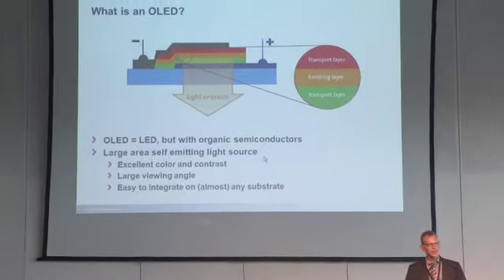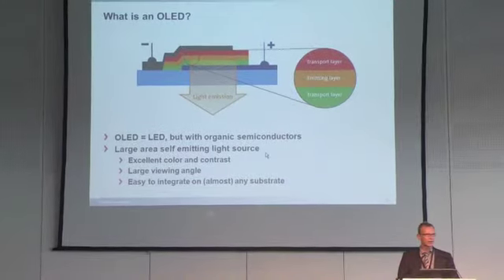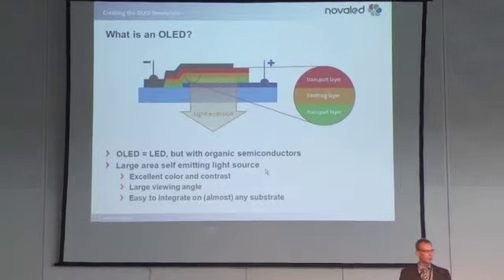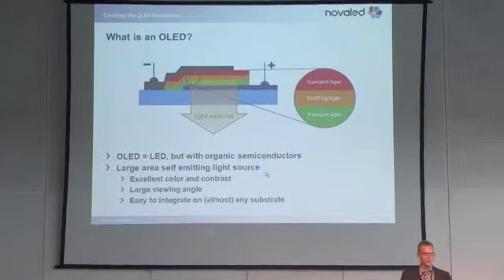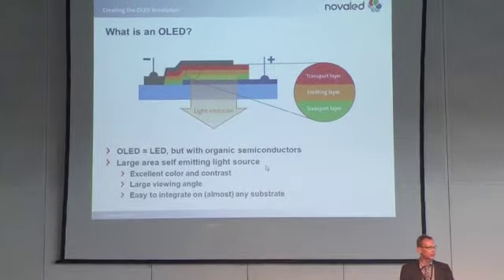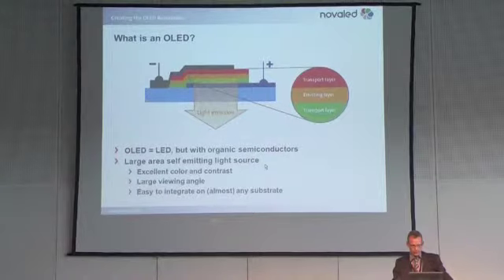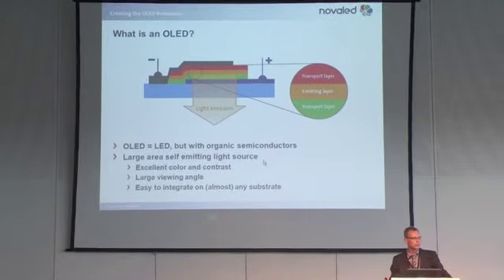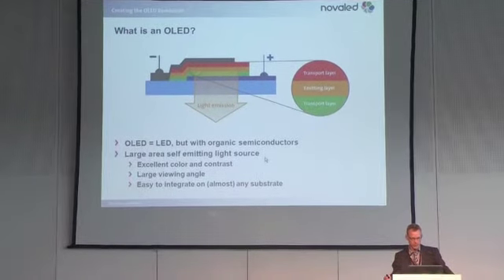One of these is that you can make every organic electronic device, including OLED, relatively easily on large area. The inorganic semiconductors always had the problem that they have to grow crystals. This was, by the way, the problem why we hadn't seen a blue LED for over a decade or so. In the 80s you could buy green LEDs en masse, but no blue LED. And just in the beginning of the 90s, the inventors solved the problem of growing blue emitting crystals on silicon or on sapphire substrate at this time.